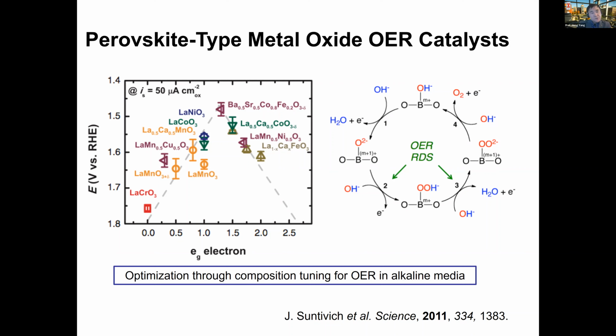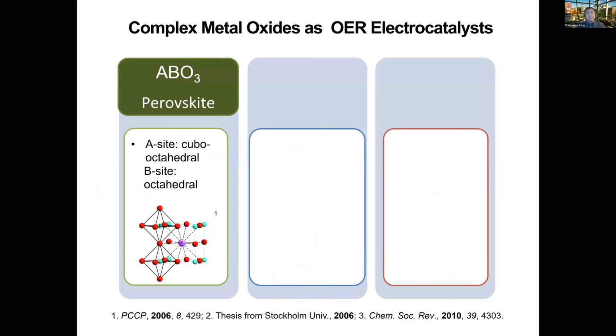This is a very nice tunable system, because if you think about this, right, you have A sites and B sites, and the tunability is tremendous. And I was also inspired by the use of perovskite, because based on my prior experience, I know perovskites have a lot of variable parameters that you can dial into while still maintaining the generic structure. And there is tolerance of defects in the system. So that means we can dial in different levels of electronic intensity of certain binding sites, all changing the oxygen.